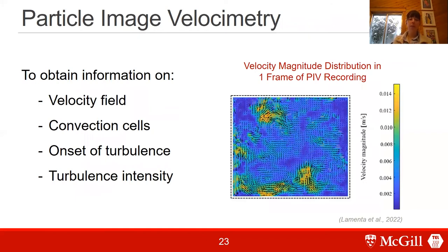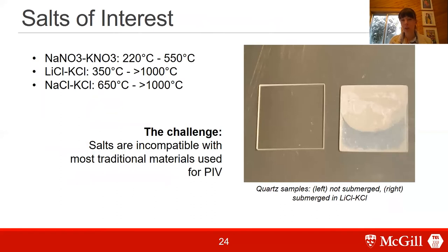So the tool that we've been developing is particle image velocimetry. This diagnostic technique is used to obtain the velocity field, the convection cells, the onset of turbulence, and the turbulence intensity, because we found that radiation will affect all of these in our molten salts when there is natural convection and radiation interacting. Particle image velocimetry is not a new technique at all. It's been used extensively in low temperature liquids such as water or in gases. But up until now, nobody has actually used it in molten salts.